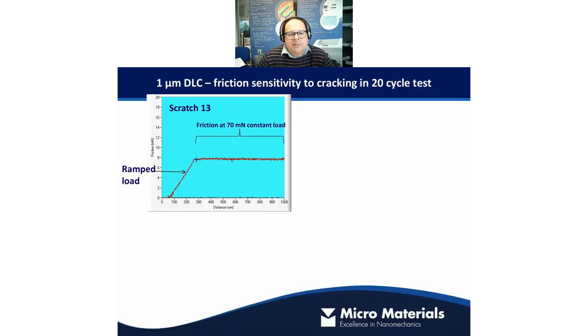So what happens in a multiple pass wear test? Well, this has got a nice example. It's a test of a 1 micron diamond-like carbon coating, and it's a 20 cycle test. What we've done is we've been using a 1 millimeter long scratch bar. So this is distance along the scratch track here, and this is the frictional force acting on the probe. And we're applying a normal force of 70 millinewtons to the sample via our probe here.